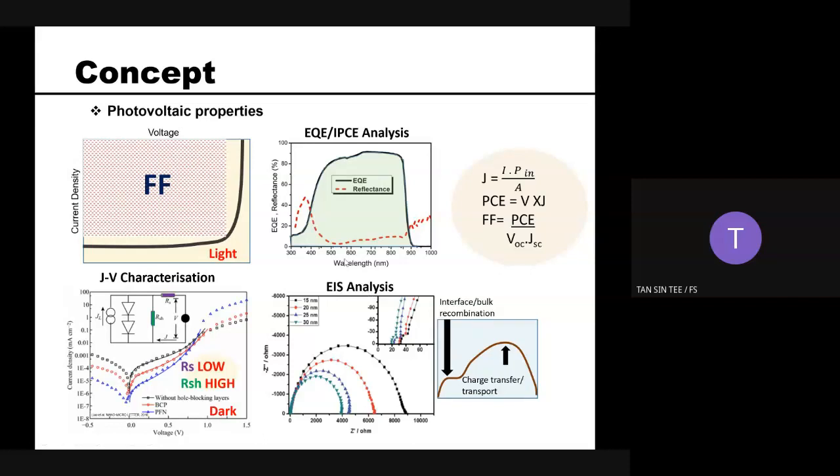Some of the scientists in our lab are also doing impedance analysis to study the charge transfer phenomenon in the solar cell. For a good organic solar cell, you always have two semi-loops because you have two interfaces. If you are working on the DSSC, because you have another interface for the dye layer, in this case you will have three loops, which show that another interface comes from the electrolyte system. Now let's move on to the two loops, which is about the OPV structure.